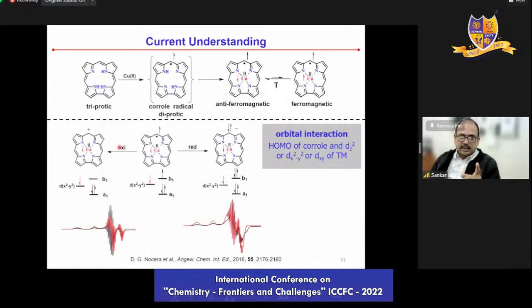They oxidized, removing one electron, and got a cation, and the copper 2 plus is residing there because only the ligand is getting oxidized, not the metal. And they are getting an EPR signal. The copper I value is 3/2. As a result, you will be seeing 4 sets of peaks. It's called hyperfine splitting. And the finer lines you are seeing are because of super hyperfine splitting, which is happening because of the 4 nitrogens you have here.